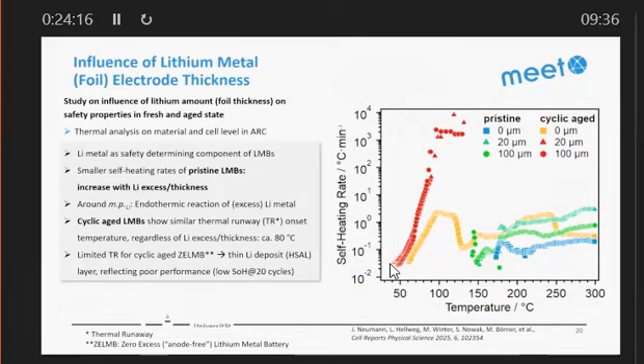And we see for the pristine cells, still everywhere lithium metal is the safety determinant component. We have a smaller self-heating rate for the pristine LMBs because we have no high surface area lithium, not such a big surprise. Around melting point, we have an endothermic reaction of the excess lithium metal. And this is actually an endothermic reaction of lithium metal. That means heat is consumed. Actually, heat is created because we are heating up, but heat is consumed also because this is used for lithium melting. And cyclic aged LMBs show very similar thermal behavior. And at 80 degrees C, everything becomes very, very uncomfortable.